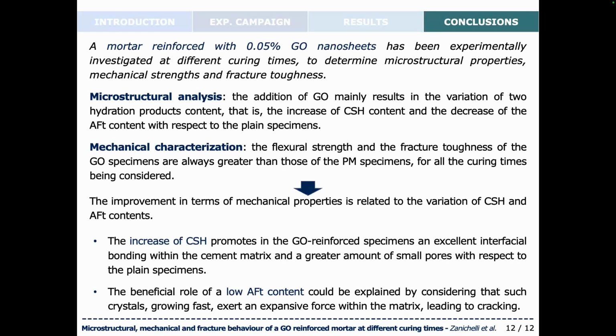In particular, the increase of CSH promotes in the GO-reinforced specimens an interfacial bonding within the cement matrix and a greater amount of small pores with respect to the PM specimens. Whereas the beneficial role of a low AFT content could be explained by considering the growing mechanism of such crystals, that growing fast may exert an expansive force within the matrix, leading to cracking. And so a low AFT content would lead to a less damaged cement matrix.